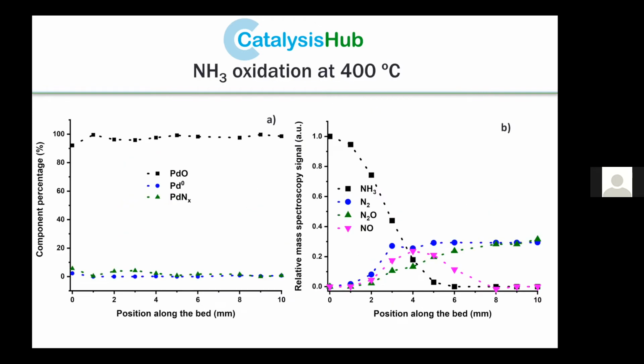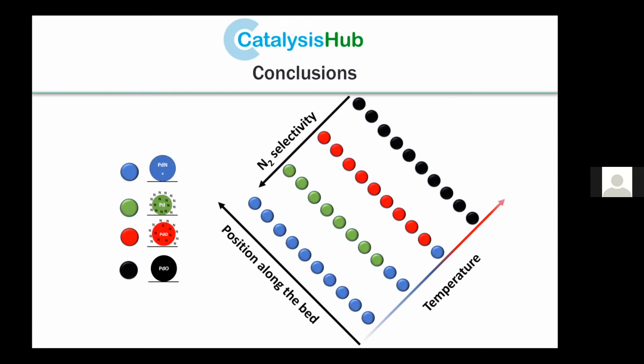And we suggest that this change of phase, which happens after position 4, where you can see palladium nitride completely disappear, although you still have a small amount, caused the complete loss of selectivity of the system. So in general, we can see that as we change position across the bed, we have a much wider variance.